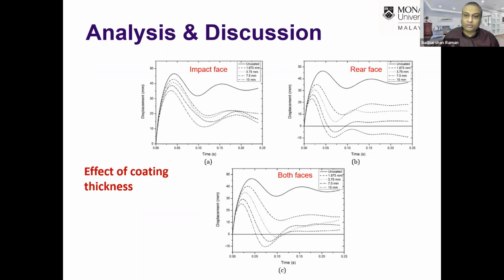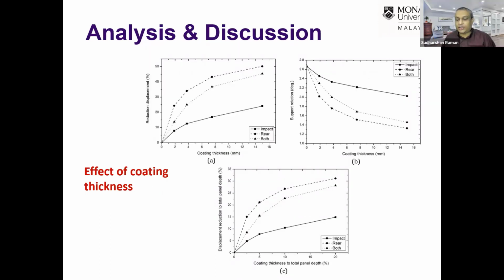thickness. So we can see here that when the coating is applied on a single surface, coating on the rear surface was more beneficial for the panel. The next stage, we looked at the coating thickness in terms of reduction of displacement, support rotation, as well as displacement reduction to the total depth of the panel. And we found that when you're coating it on the rear surface by using this type of polyurethane, it is more beneficial to the panel.